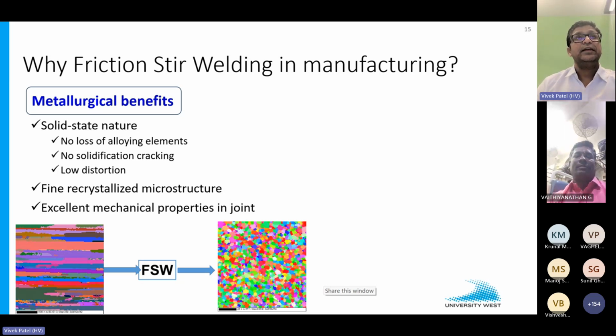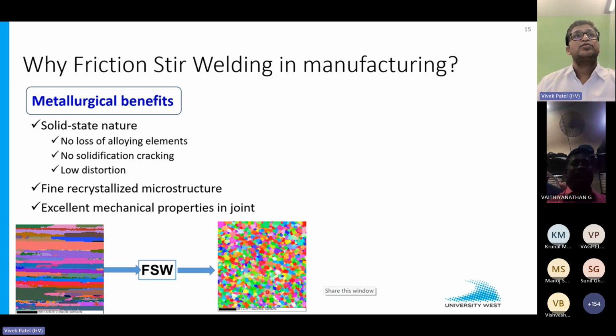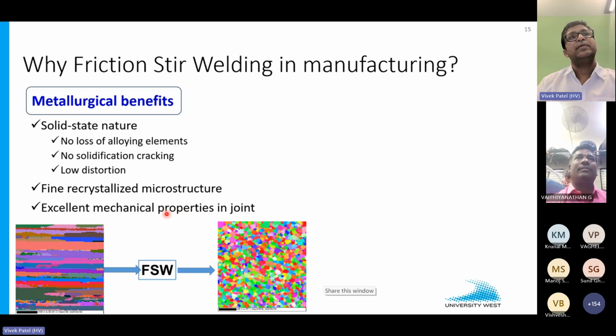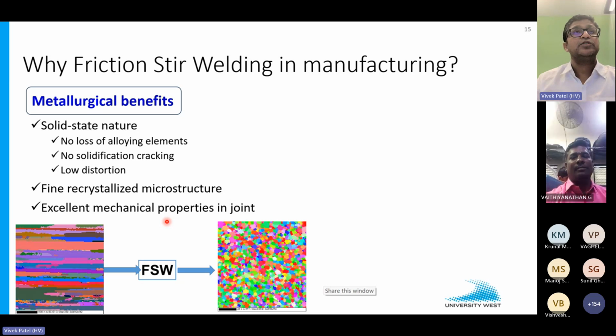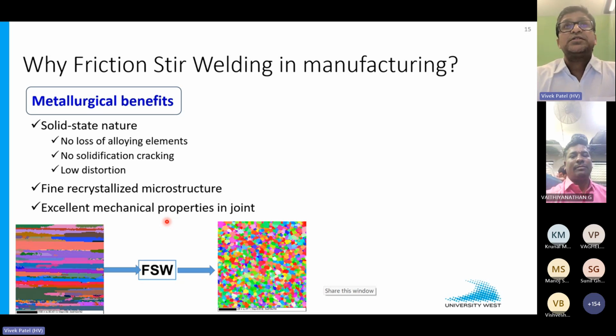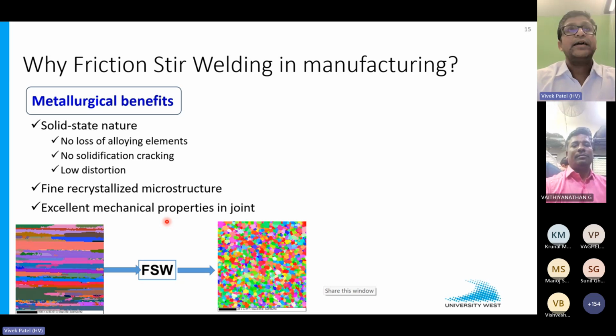And this fine structure basically helps to gain some properties in the nugget, and ultimately you have the stronger joint. So that fine structure contributes to the mechanical properties. When we talk about the mechanical properties at room temperature in a static way, the static tensile strength, the joint always fails either from the heat affected zone or from the parent material itself. This process gives almost 90 to 95% of joint strength. So in terms of mechanical properties, friction stir welding guarantees better strength compared to the fusion joining methods.